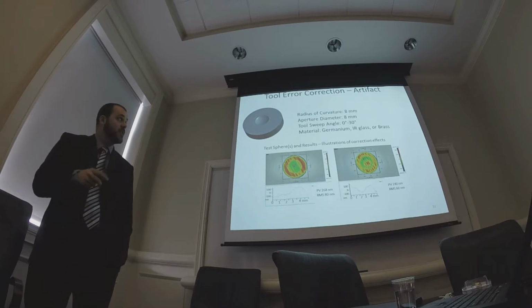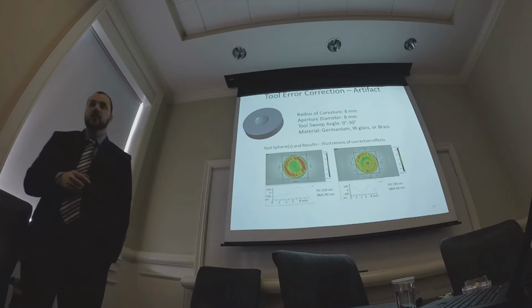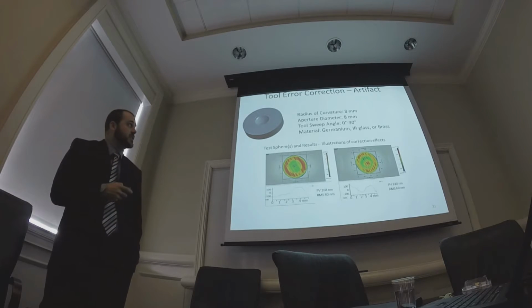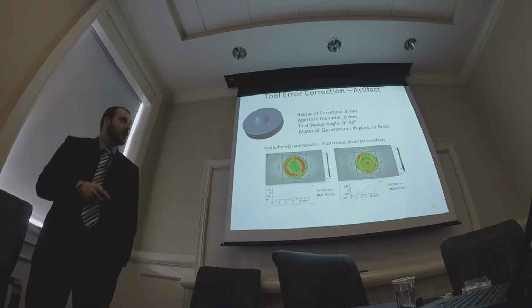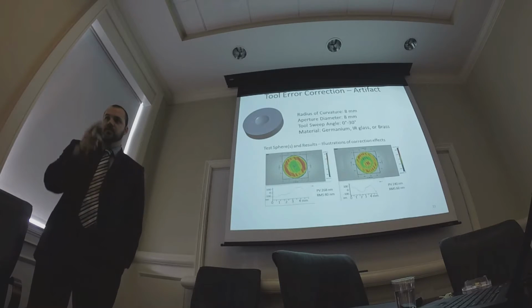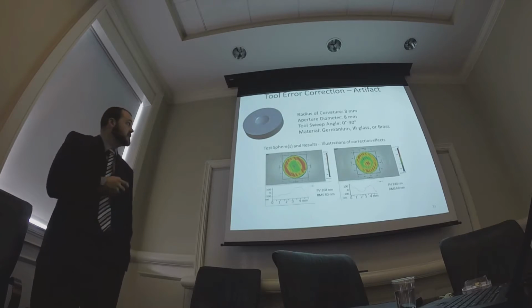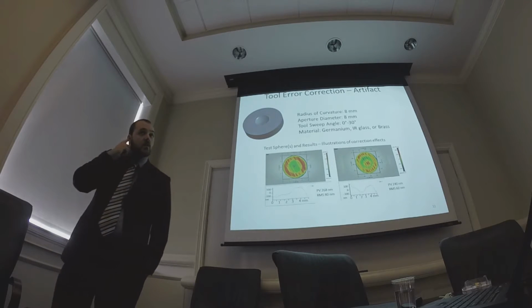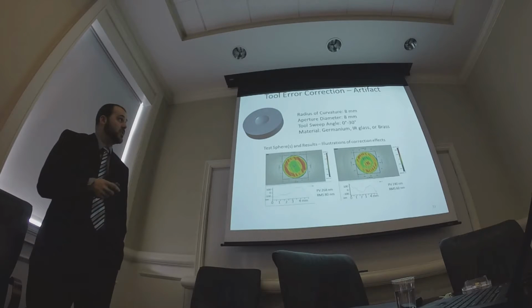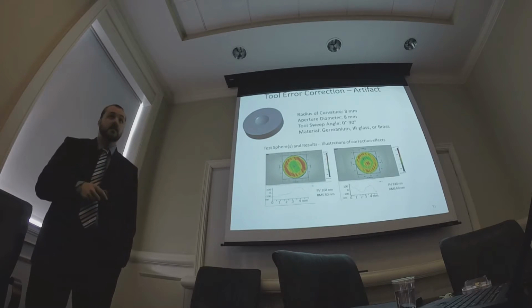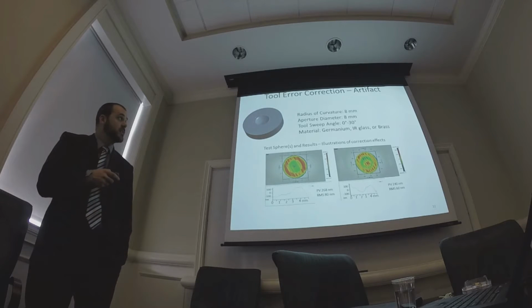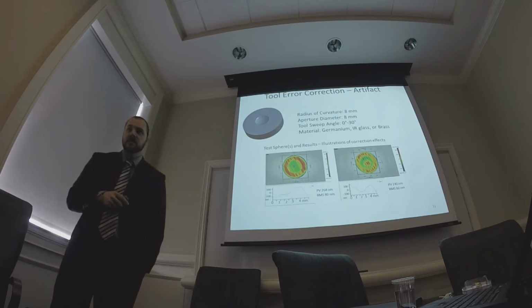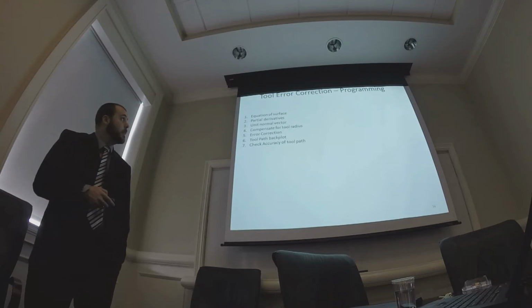So this is the artifact-based method. The 8mm radius of curvature, 8mm clear aperture results in a tool measurement of 0 to 30 degrees of the tool. The full angle across this is 60 degrees, but you're only cutting with one side of a turning tool, and with a milling tool, it's sweeping around. So you're going to map 30 degrees of the tool onto this surface. We did this in germanium, IRG26, and brass.